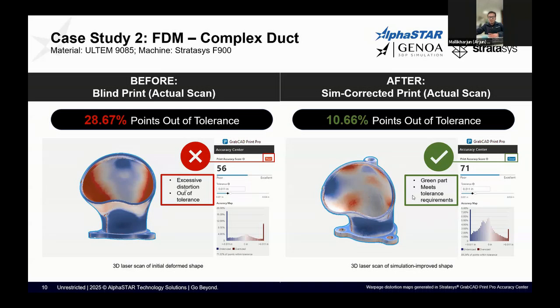Once we printed it, if you look at the number of points out of tolerance, previously the blind print was 28.67% out of tolerance. And now just by running one virtual simulation loop, we are able to bring it down to 10.66% out of tolerance. On the score, the scoring scheme is a Stratasys specific scoring scheme. So here we went from 56 to 71, which made a poor print or a bad print into a good print above 70. So we are able to reduce the excessive distortions and create a green part, which meets the net shape requirements.